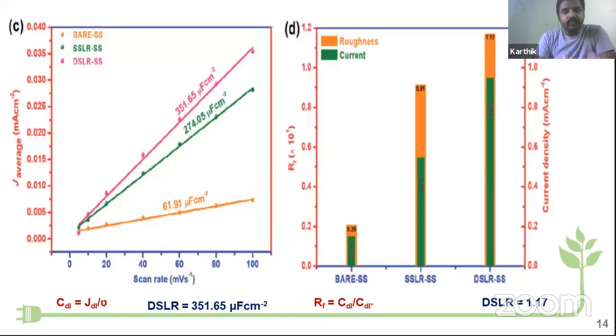Using this double layer capacitance, we can determine the roughness theoretically using the formula RF equals C_DL divided by C_DL of the smooth surface, which is nothing but the smooth surface double layer capacitance. For example, smooth stainless steel has 61.91 microfarad of double layer capacitance. This is the experimentally calculated one. Again, the double side laser roughened stainless steel gives a high exchange current density as well as roughness value.